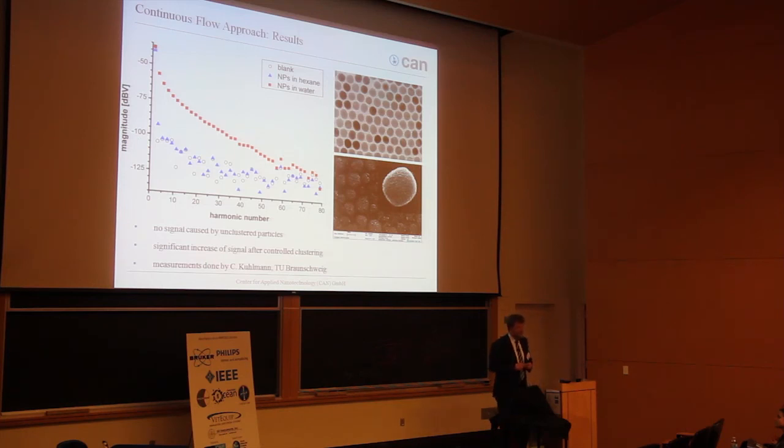It looks like the blank, but if we take the micelles here, which are all formed with the particles, so approximately a size of 170 nanometers, so quite a lot of them, you see that there's some kind of change in the MPS measurements. So these are really very raw results. I'm not quite sure about them. We definitely have to repeat them, but maybe it looks like there is an influence if you use the clusters.